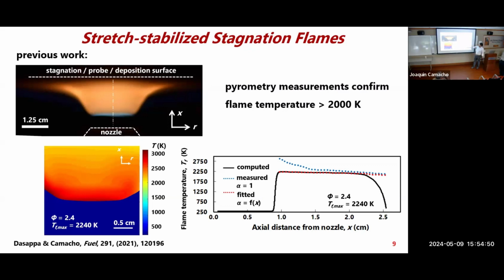But then we do a less independent measurement. We kind of hybridize, saying that the optics give us this temperature, so we fit this parameter here to give us good agreement. So this is less independent. The question is whether these are reasonable, physical values. They are physical values, typical of carbon. One could have believed those computed values, I think.